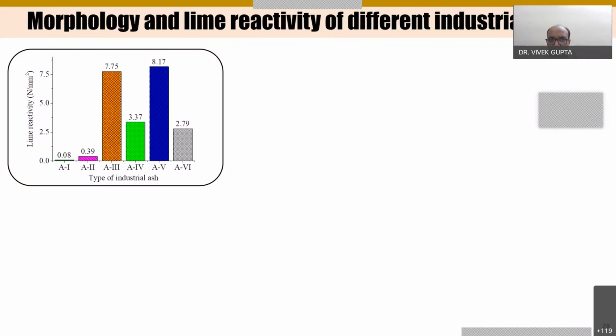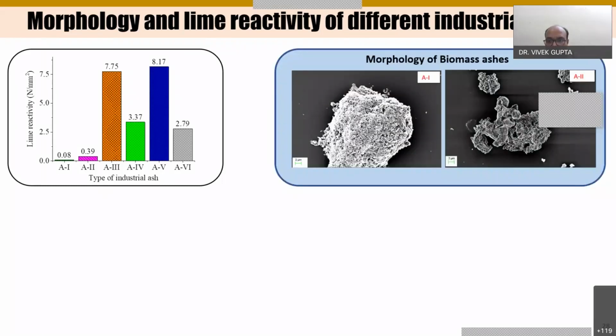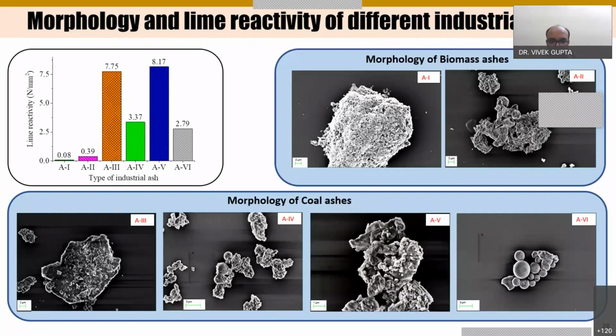studied the morphology of the different industrial ashes, and we found that the irregular shaped ashes, like you can see the A3 and A5, they show the better properties when we go for the lime reactivity. Like in the literature also, the researchers have reported that whenever we have the angular characteristics of the particles, it gives the better mechanical properties due to the interlocking effect.